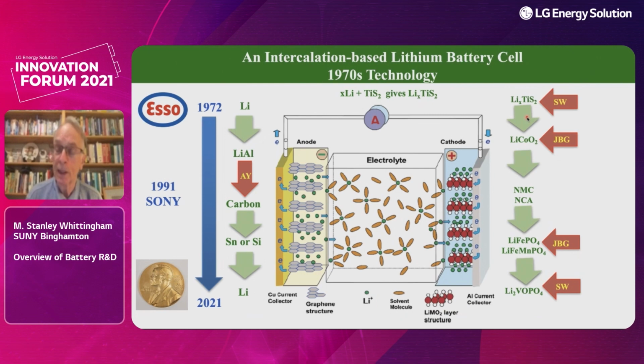John Goodenough was working on lithium cobalt oxide. Its magnetic properties, recognized the structures were the same, decided to test cobalt oxide, and this raised the voltage from about 2.5 to 4 volts. And this has been the workhorse for all electronics batteries from 1990 to the present day. Clearly, cobalt has to go, so that's why we've gone to NMCs and NCAs. And eventually, I think we'll show in a minute, nickel and cobalt will have to go also.